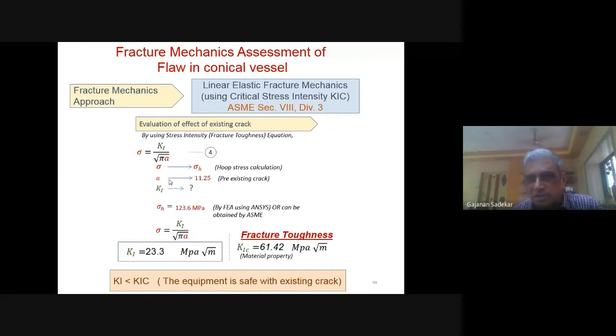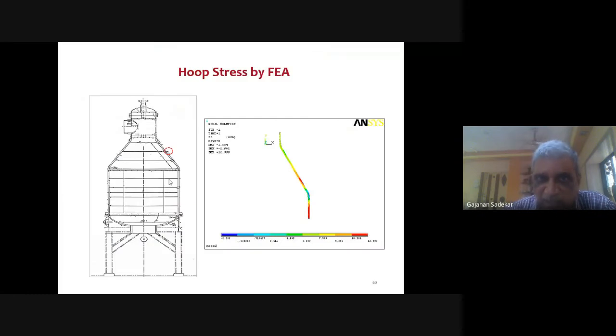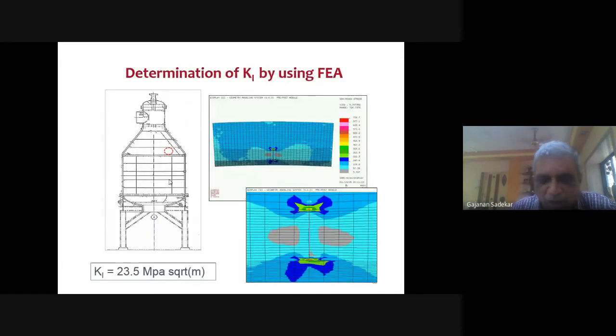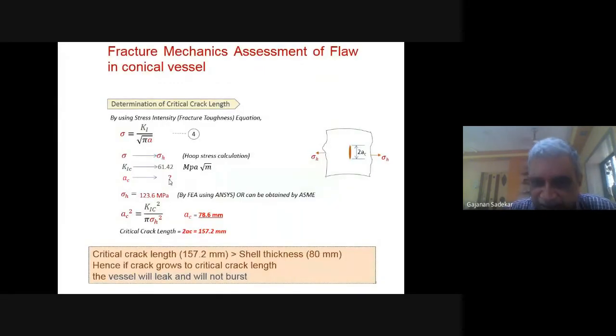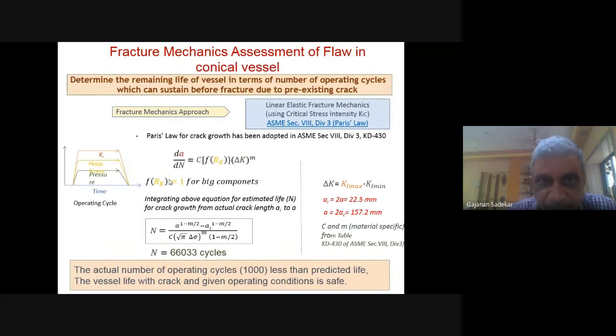Further we calculated the crack growth rate and all that. This KIC was calculated using the ASME section 8 division 3 because the methodology is given there. But we also did the FE analysis to find out the KI value, and you can see more or less the same 23.5 KI value came in both cases. So it looked okay. Then we further did the calculations of the critical crack length, and the critical crack length was much higher than the actual thickness. So we said that the vessel will leak and will not burst.